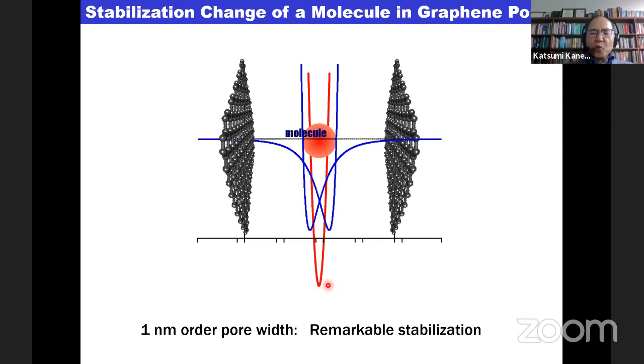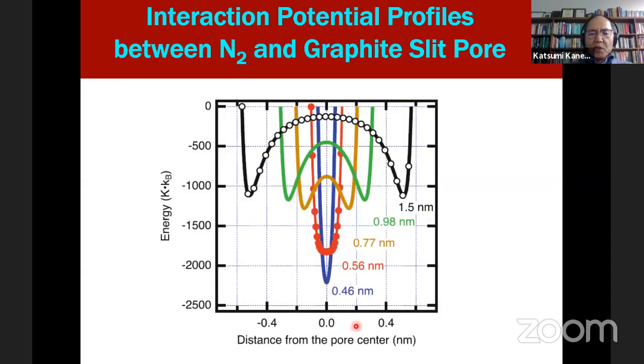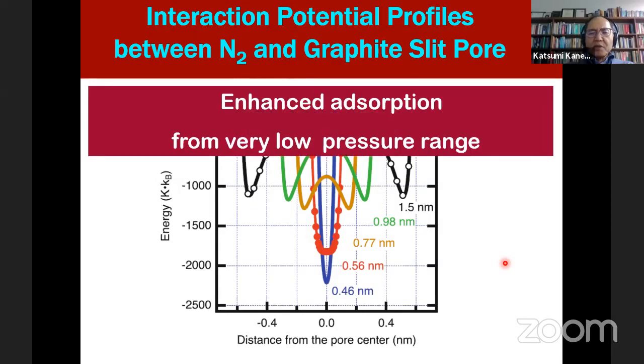Then nanoscale pores have such a very, very strong, deep interaction potential, with a very strong ability for catching and storing molecules, vapor molecules in particular. Here I will show you the interaction potential change for nitrogen and graphite slit pore. With decreasing pore width, this potential minimum becomes deeper and deeper. So a smaller pore system has a very deep interaction potential, giving very unique enhanced adsorption. Even from very, very low relative pressure, adsorption starts.